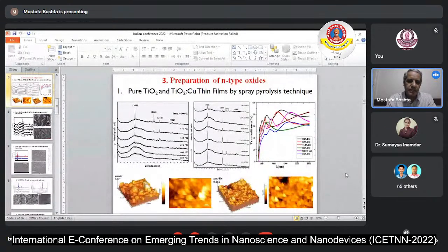First of all, I start with titanium dioxide. Titanium dioxide, as everybody knows, is an important material in the photocatalytic area, and we also try to deposit it by spray pyrolysis. Looking at the deposited layers, we have many different temperatures for the spray pyrolysis technique to get a high quality material. We found that at high temperature, about 500 degrees, we have good crystallinity and a good material.